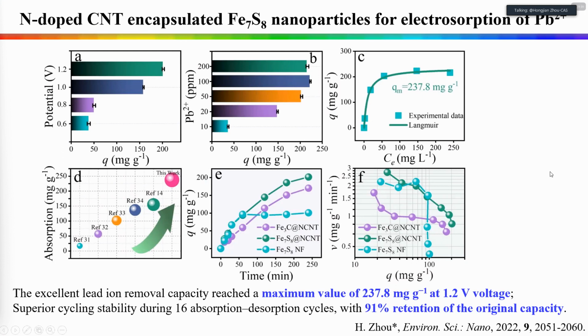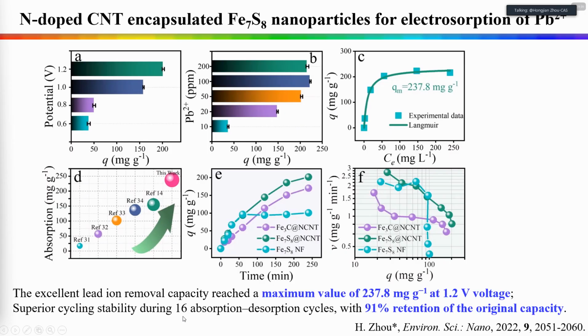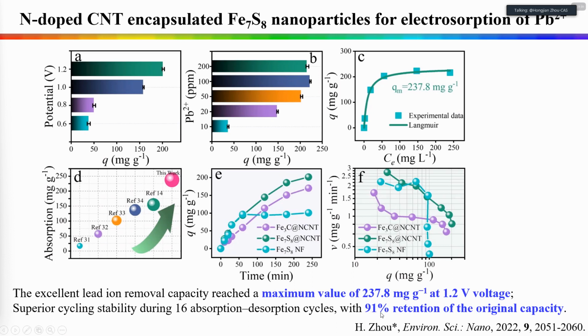So this is the CDI performance. We can find our material shows excellent lead ion removal capacity. The maximum value can approach 237.8 milligrams per gram at 1.2 volts applied voltage. And also the material shows superior cycling stability during 16 adsorption-desorption cycles, and it maintained about 91% of the original capacity.